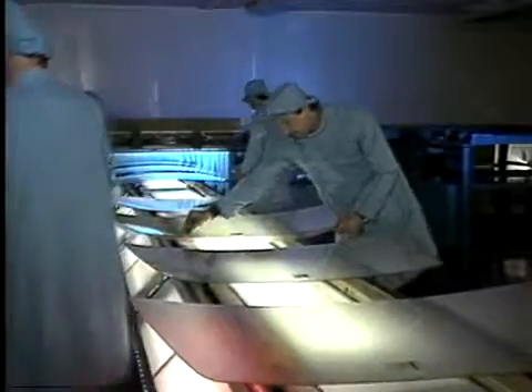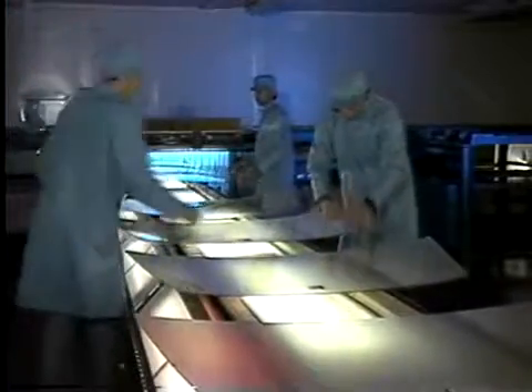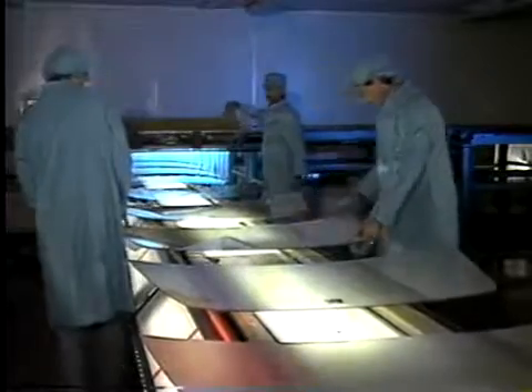Laminated glass, on the other hand, is ordinary window glass, but it is given its safety by the incorporation of an interlayer, these days, of PVB, or polyvinyl butyral, which is a very stretchy material, so that if you do have the misfortune to hit it with your head, it acts as a safety net and stops you from being ejected from the car. Less important now, of course, because seatbelt legislation and airbags do tend to stop people hitting the windscreens anyway. Glass to make laminated windscreens is much thinner than your other car glass.